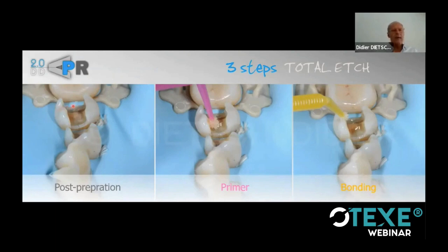We are having an opening, an occlusal opening, which is much more than 1/3 of the buccolingual width. My preference, I don't have the time to go in details, but I want to mention this at least, that my preference today is to go with the classical 3-step total etch or etch and rinse. In fact, the key for long-term stability of adhesion, dear colleagues, is to get a separate bonding step.